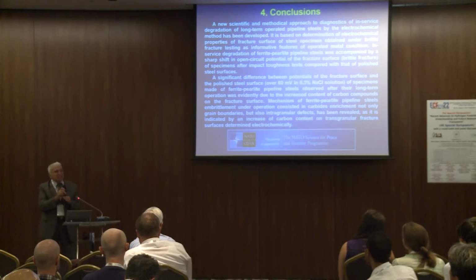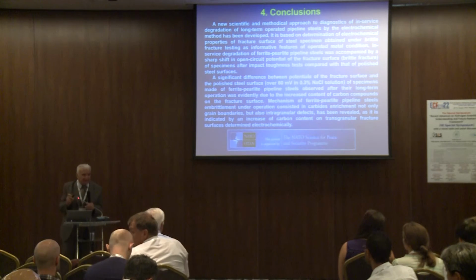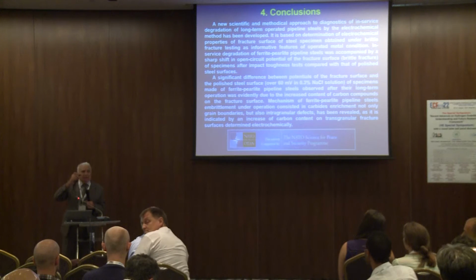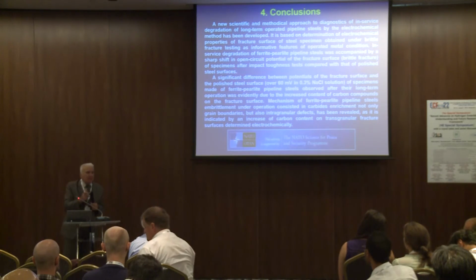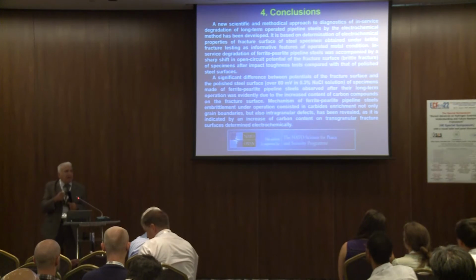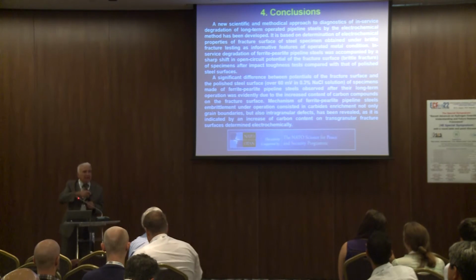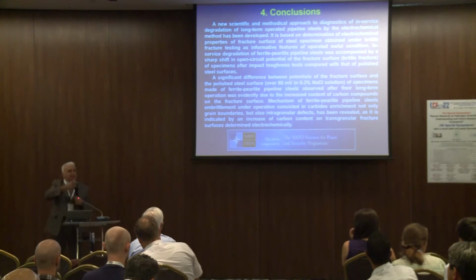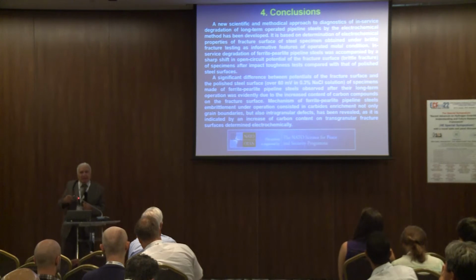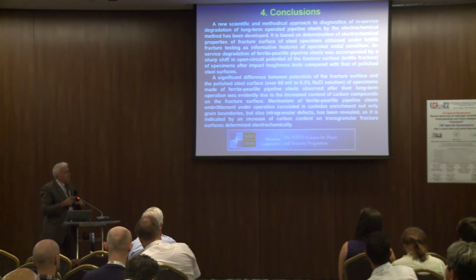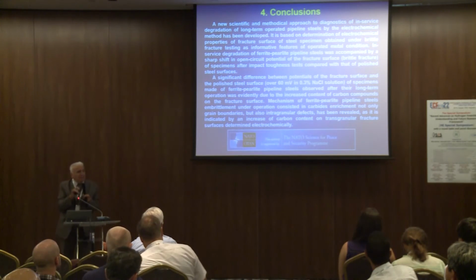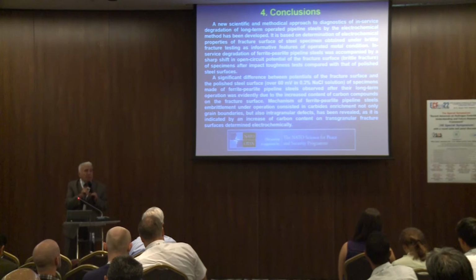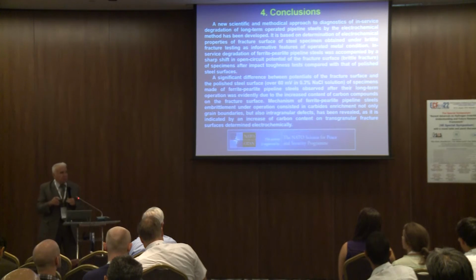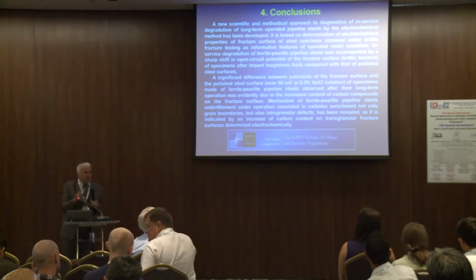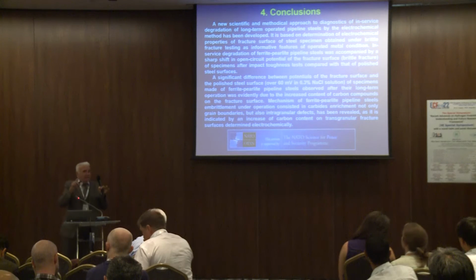We use very simple electrochemical parameters. It is corrosion potential. In our experience, polarization resistance and corrosion current are more sensitive to material degradation than potential. However, in this case, we need to calculate the real area of the fracture surface and calculate the real density of, for example, corrosion current. And it is possible, and we expect that when we use another electrochemical parameter more sensitive to material degradation, we should get more difference. These parameters measured on the fracture surface will be, in our opinion, more sensitive than potential.